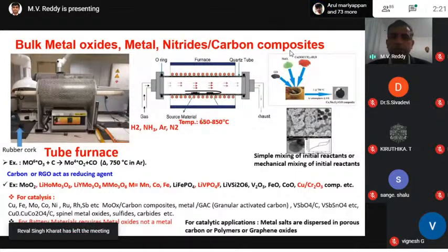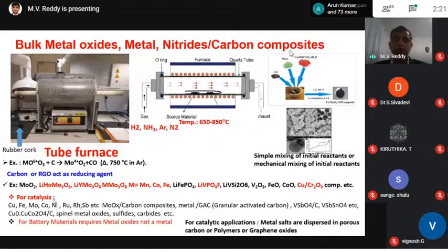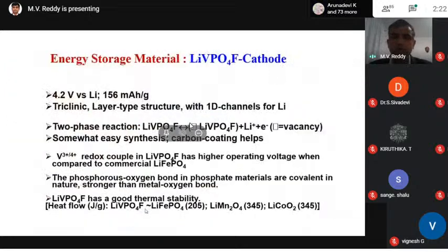You can heat the sample at 650 to 850 degrees, and we are able to get the respective oxides. So it's very important. If you work with catalysis, there we need metals or a metal oxide with more carbon. That's why, depending on applications, we have to get a different one. So this is one example.